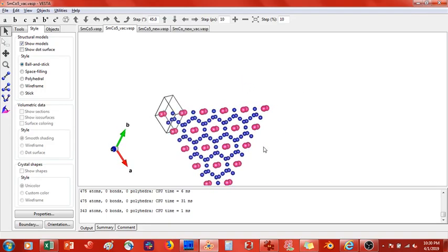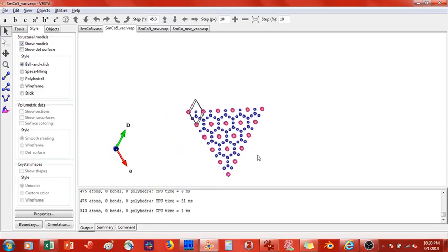Okay, so those are your two options if you have a unit cell whose unit cell axes are not orthogonal. You can either just figure out which atoms need to be deleted and add your vacuum that way, or make the unit cell axes orthogonal through the procedure I showed you, where you expose internal planes as the new external planes, such that the intersection of the new external planes forms a 90-degree angle.